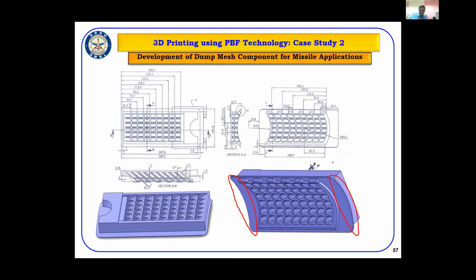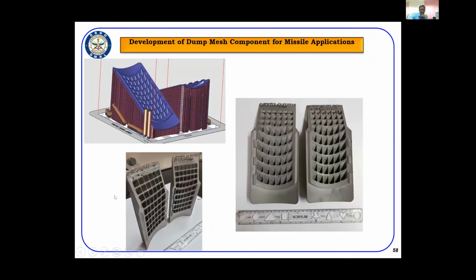So due to these limitations, the rate of production was also very low, and we thought this would be one other component which can be taken up for consideration of 3D printing, and we went ahead with the development of this component. After the initial design review, the most appropriate orientation of this component with the minimum support structures was found using the simulation, and these are the support features that were required, and these are the specimens in different directions that were also considered.